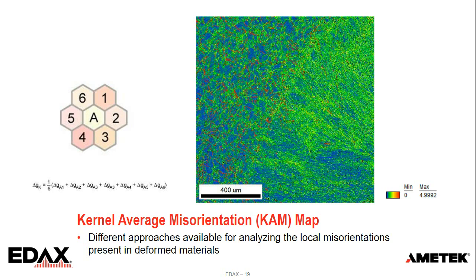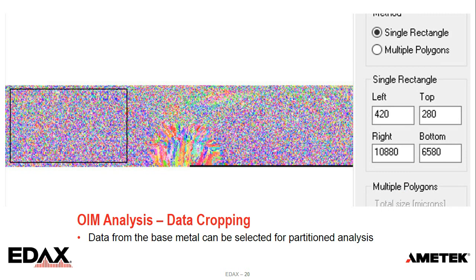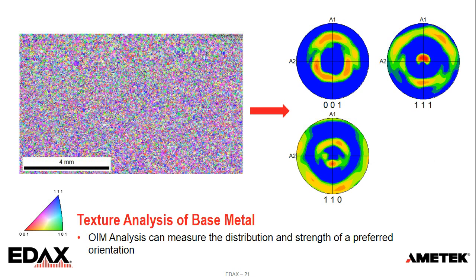Now, I started off with this very large data set to get an idea of a large scale of data. Once we have that data, we can also do cropping. So I've just come in here and said, show me a region of the base metal. In this case, it's just a rectangle we've pulled out. Once we have that, we can do what we call texture analysis. Texture analysis is just looking at the orientation distribution of the measured orientations. It fits a function that describes the distribution. From that, we can get an idea of the strength of a preferred orientation.